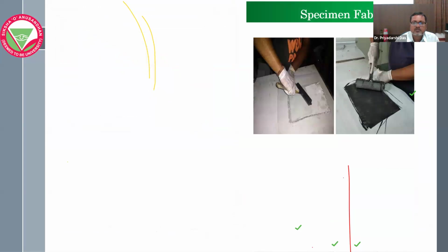Now the specimen fabrication, we have used two specimens, glass epoxy and carbon epoxy. In these two figures, the specimen is fabricated like I said in the earlier slides, where the fibers are placed one after another, and in between is the matrix. The fiber is meant to carry the load, and the matrix distributes the stresses between the fibers to protect it from the external environmental loading.